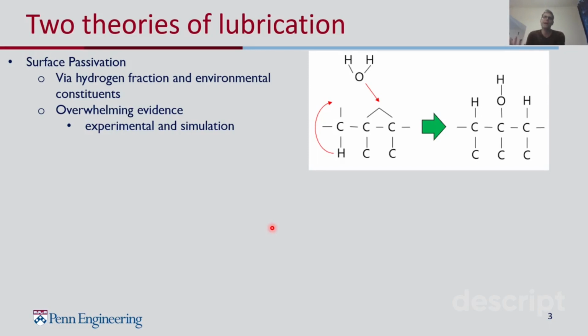This is done by, in some cases, doping with hydrogen. So some of this hydrogen can end up on the surface, and so you'll have a hydrogenated surface that doesn't tend to form bonds. If it's not doped with hydrogen, you can actually get passivation from the environment. In this example, water molecules can actually land on the surface, dissociate, and then terminate dangling bonds with either hydroxyl groups or hydrogen atoms, which in both cases tend not to form additional bonds